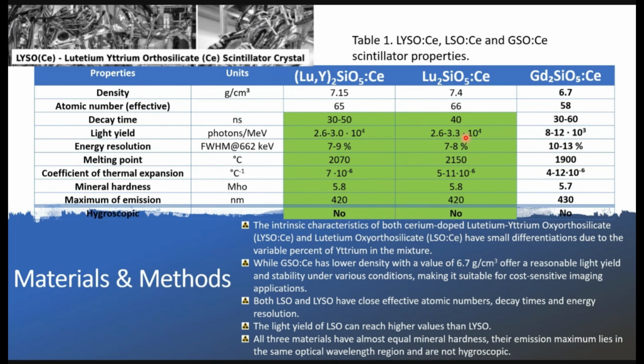The third, the cheaper material, the gadolinium-based material, has lower density and effective atomic number. The decay time is in the same region as the other two. However, as we can see, it emits much lower light than the other two. The light yield is much lower. It has worse energy resolution compared to the other two materials. It melts at lower temperatures. The hardness is almost the same value as the other two, and it emits in almost the same wavelengths. All three materials are, of course, non-hygroscopic for these applications.